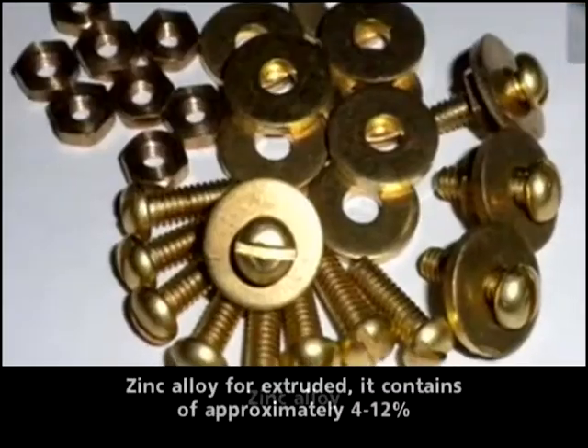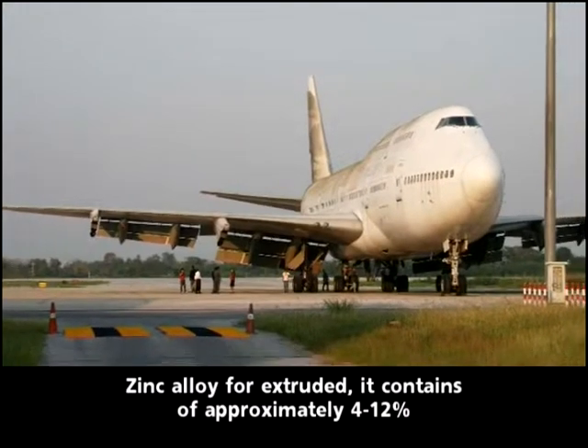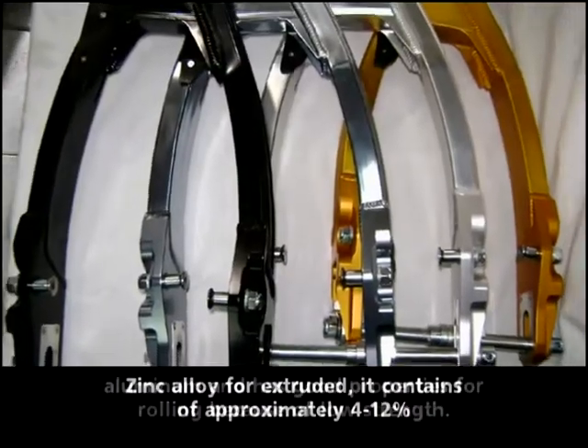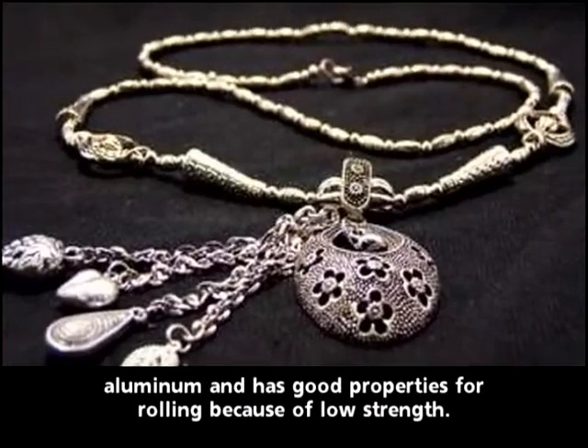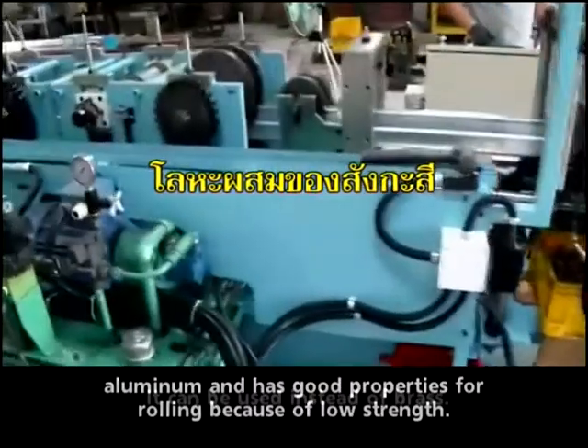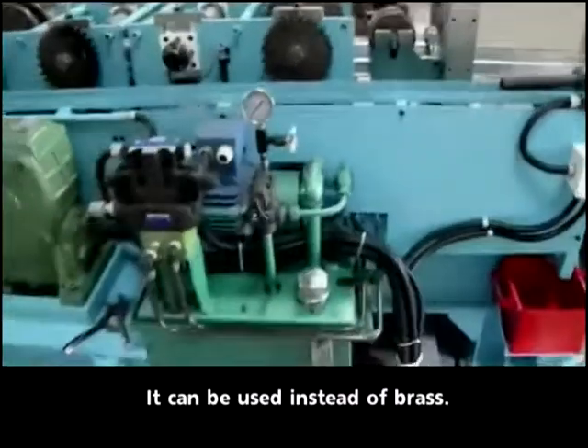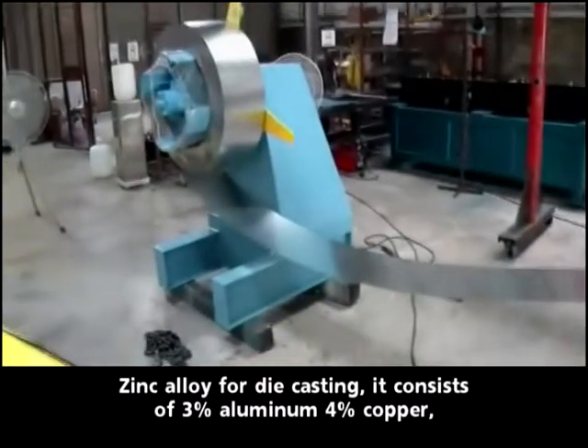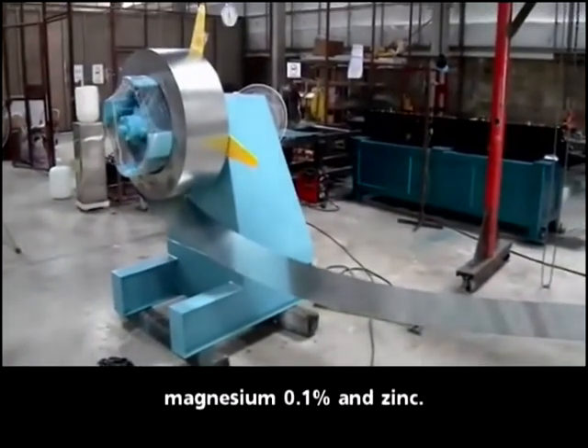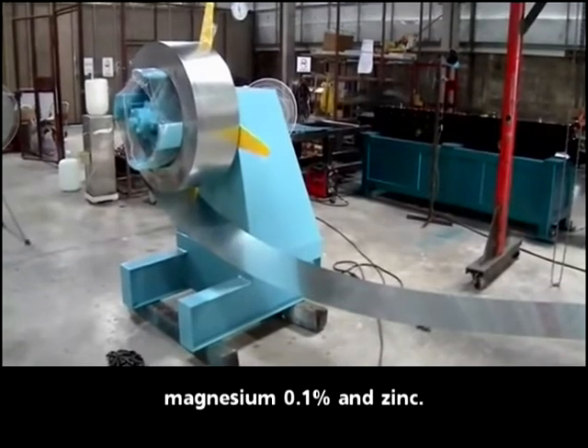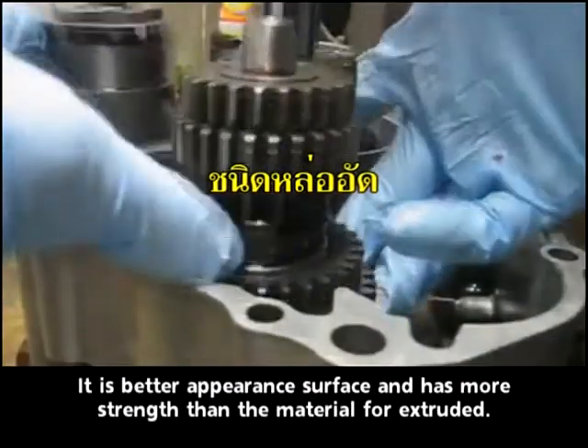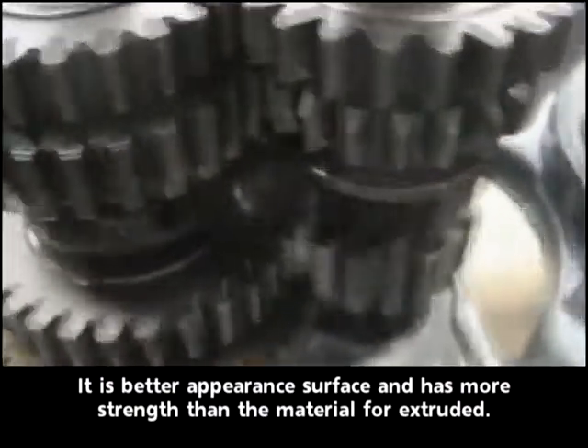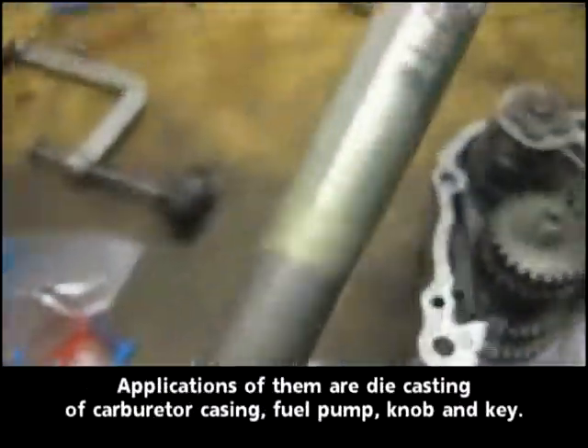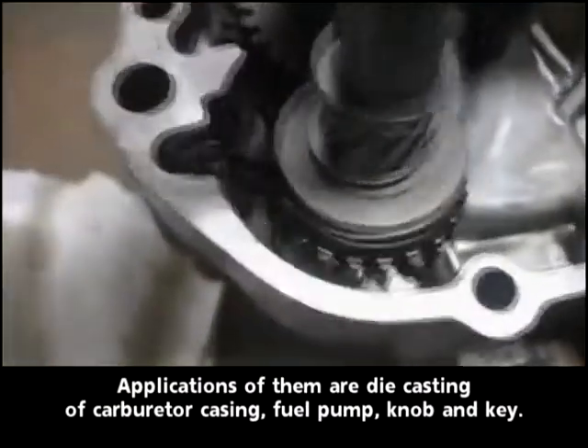Zinc alloy. Zinc alloy for extrusion contains approximately 4 to 12% aluminum and has good properties for rolling because of low strength. It can be used instead of brass. Zinc alloy for die casting consists of 3% aluminum, 4% copper, 0.1% magnesium and zinc. It has a better surface appearance and more strength than the material for extrusion. Applications are die casting of carburetor casings, fuel pumps, knobs and keys.